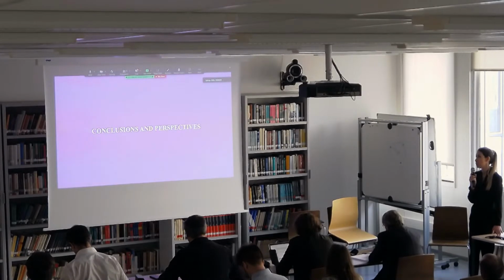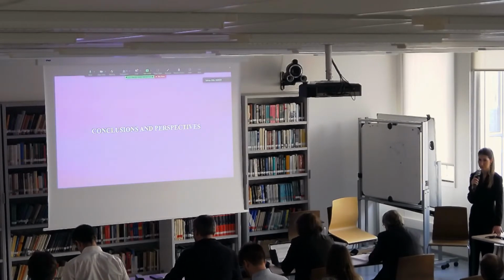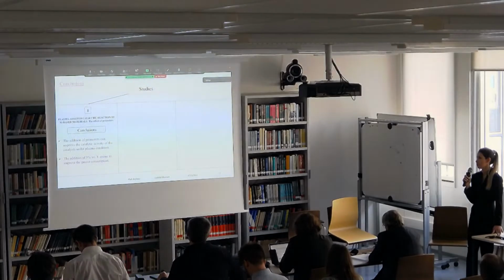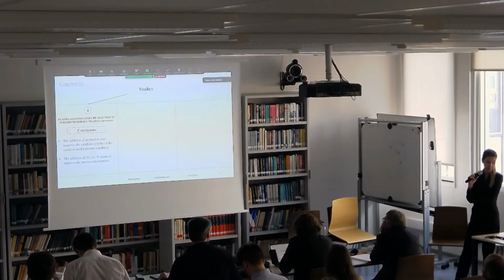So to conclude and see perspectives, first I'm going to give you a small conclusion. We already studied the effect of promoters in nickel ceria catalyst. We see that with the addition of promoters, the catalytic performance can improve based on their type. With the first series of 5% loading promoter, yttrium has the best catalytic performance. But not only the type of promoter, but also the loading plays an important role. In the second group, the 1La promoted sample showed the best catalytic performance.